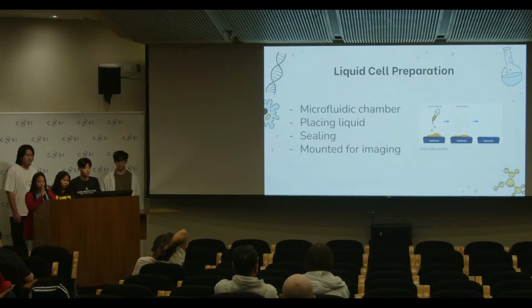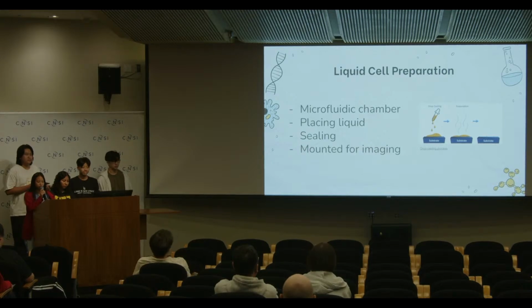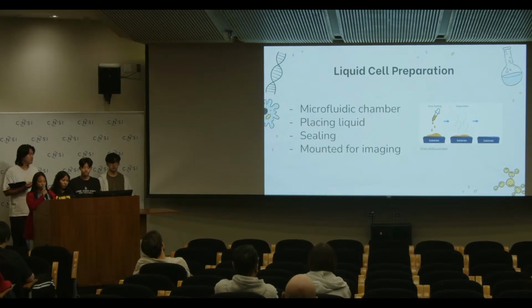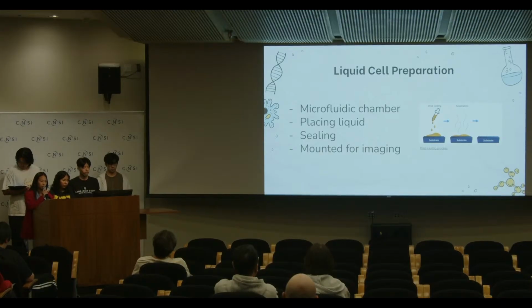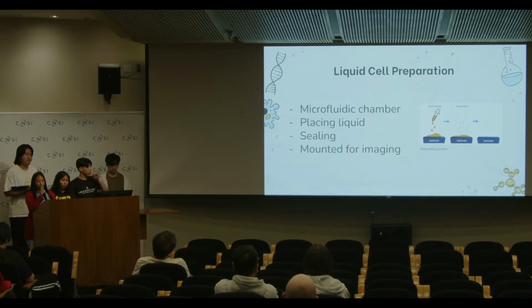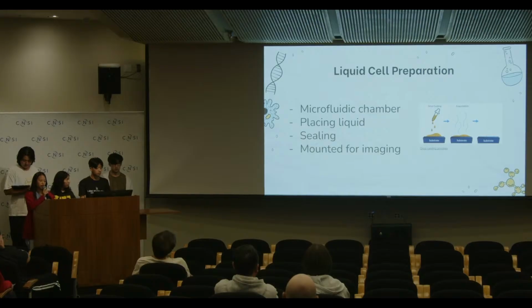There are spacers on the chips that control the thickness of the liquid layer, which is typically within a few hundred nanometers. The chips are then sealed with O-rings, which prevent fluid or air from escaping as they act as a sealing device. Adhesives or mechanical pressure can also be used. This is done in an air-free or solvent-saturated atmosphere to prevent bubble formation and evaporation. Next, the liquid cell is mounted on a special TEM holder for imaging, paying attention to avoid air bubbles, overfilling, or damage.